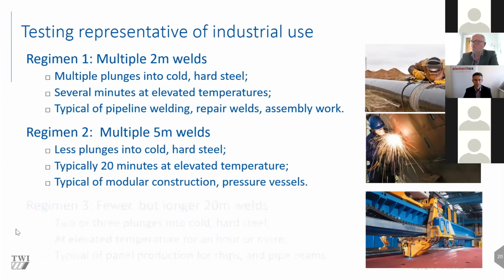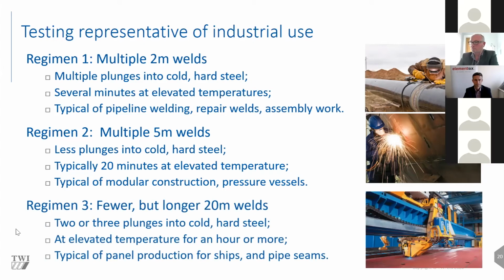And then the final testing regimen that we've been looking at is making just a few welds per tool, but these being much longer, typically 20 meters long, typical of something like welding the seam of a pipe or making a stiffened panel for a ship. And under those circumstances, the tool itself may be sat baking at temperature for well over an hour. So that gives 3 very different lifetimes that the tool may see, and it was essential that the tool could actually survive all of those if it was to be industrially useful.